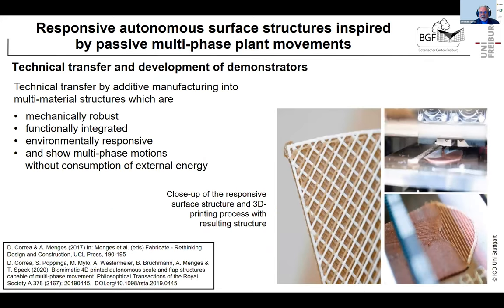What did we do then? We did 4D printing. So we wanted to make a mechanically robust, functionally integrated, environmentally responsive system, which could show multi-phase motion without consumption of external energy. And for this, we used a kind of supporting structures. These are the white elements. This is ABS plastic, simple ABS plastic. And the actuating system here in brown is a copolymer with cellulose microfibrils in it, which swell if it's wet and shrink if it's dry.